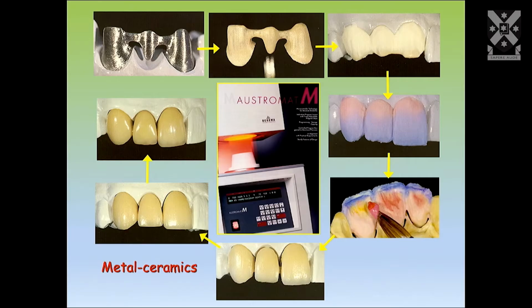So before I go into more detail on that, let me give you an insight as to how we veneer porcelain to these substructures. So up here is a metal framework that we wax up and cast. Now that could be metal or it could be a ceramic like zirconia. It's just the framework. And then at each stage we put a layer of porcelain on, which we then fire in one of these furnaces to 930 degrees centigrade. And there's a series of firings as we go through because the porcelain shrinks when we put it on, and it can have up to 8 firings depending on the size of the restoration.